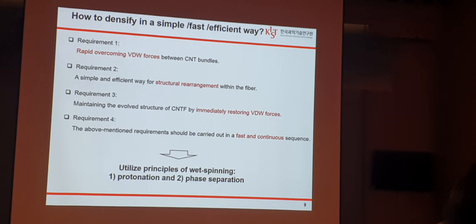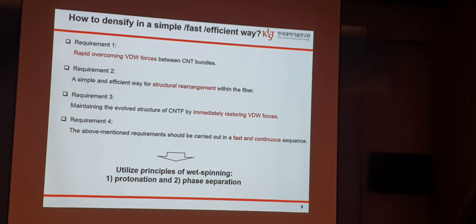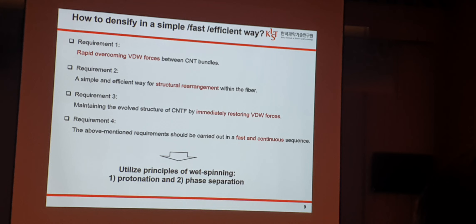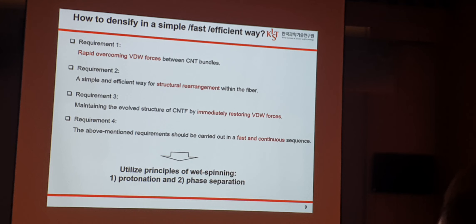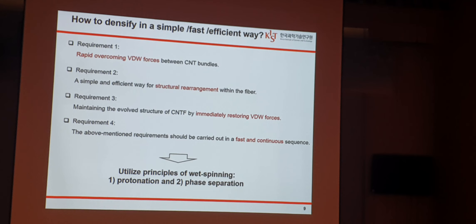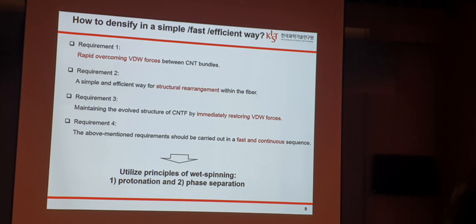How to achieve densification in a simple, fast, and efficient way? Several requirements should be addressed: rapid overcoming of van der Waals forces, a straightforward method for rearrangement within the fiber, and these steps must be carried out in a fast and continuous way. We came up with a densification idea inspired by the principles of wet spinning, which involves protonation and phase separation.